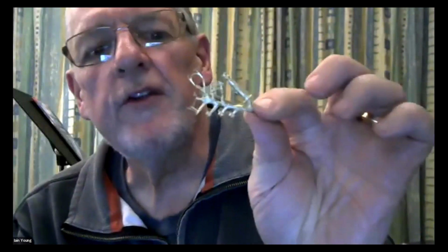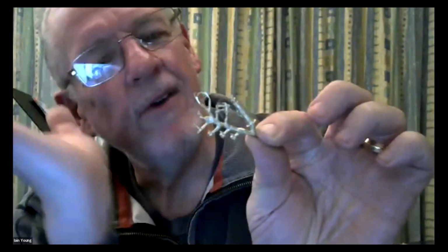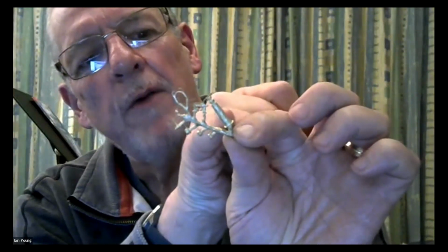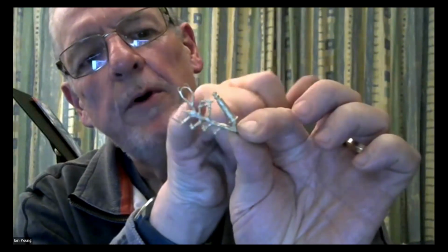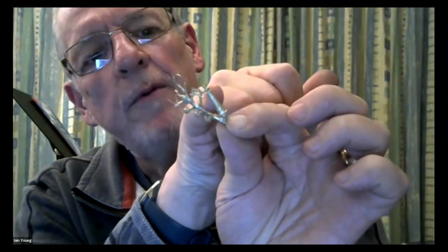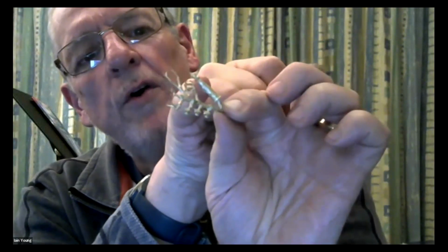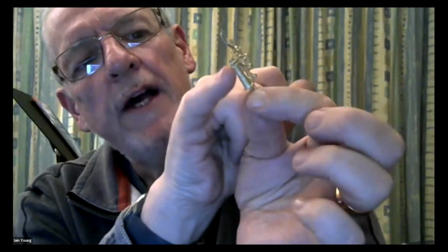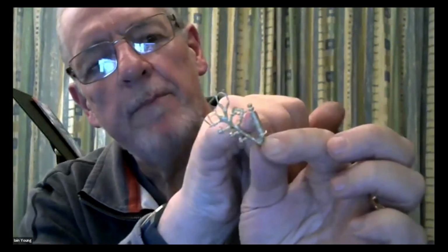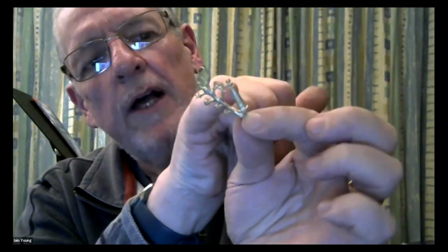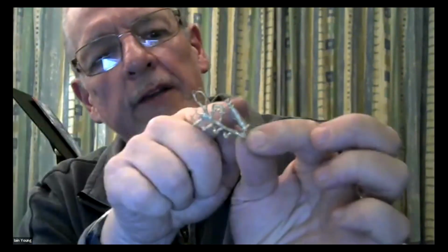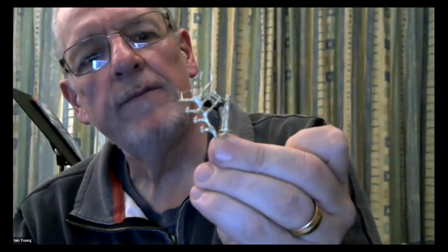Now this is a sprue. You can see the sprue. On here you have a Great Western again, but it was a perfect example of a Great Western loco jack with the support and various other bits and pieces. But in the top of that, the little ball section has holes all the way through. Do that again, you have wire in the mold. You can't rely on the rubber. The rubber would tear, break. So we have wire in the mold to allow us to have those hollow. So when you mount them on the foot plate, our little, what looks like a lamp bracket here, can then go and support that end of the loco jack. So we can do that kind of thing using wire as a core plug.